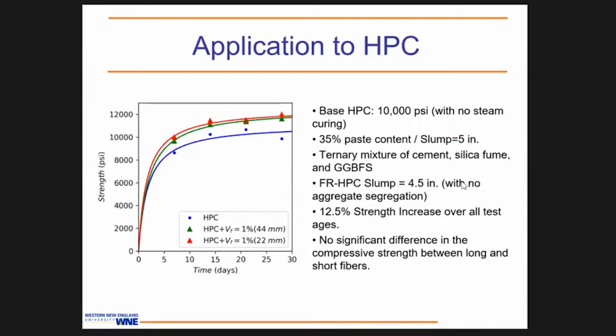So we now get our baseline for the high performance concrete. For the baseline, we are aiming at 10,000 PSI at 28 days with no steam curing. We added, actually tested, 2 fibers, although we know that we're going to work with the 22 millimeter wire fibers. We tested 2 types, longer and shorter, and both of them show similar results. The strength increase was not much different. So 22 millimeter wire and 44 millimeter wire show similar results. And also the slump, we didn't lose much. We are having about 5 inches or 4.5 inches of slump.